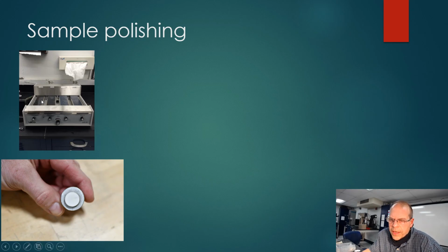These grinding stations that I have in my materials lab have different grits of sandpaper: 120, 240, 400, 600. A reminder that the higher the number on a sandpaper, the finer the grit. We don't need to start way down here. We are going to actually jump to 600, and I'm just going to gently go back and forth and polish my sample.